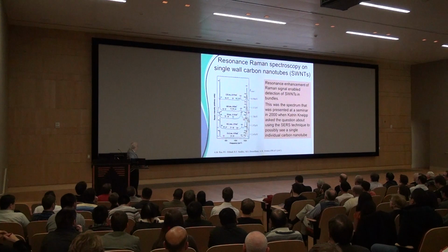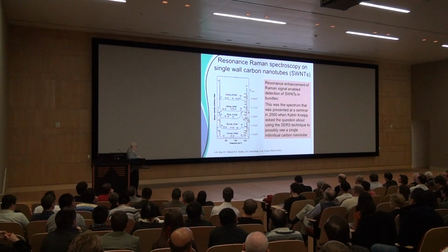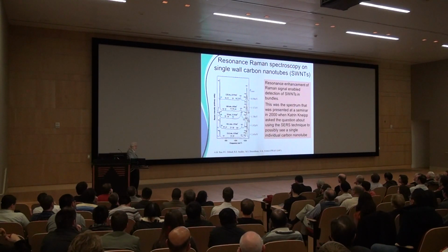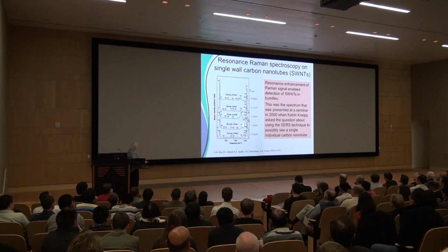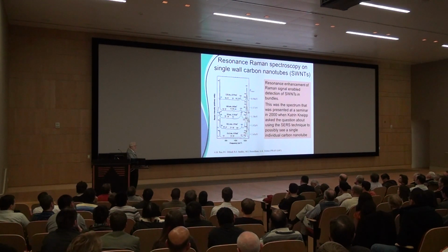And so it shows that the effect is resonant, as I showed in the previous view graph with the electron density of states with the different peaks. And so depending on the photon energy that excites the electron from the valence conduction band, you see that this vibration, that's this breathing mode, optical breathing mode, looks very different for different excitations. It has a little different frequency, different line shapes, and so forth. And that's because of the different metallicity of the samples.